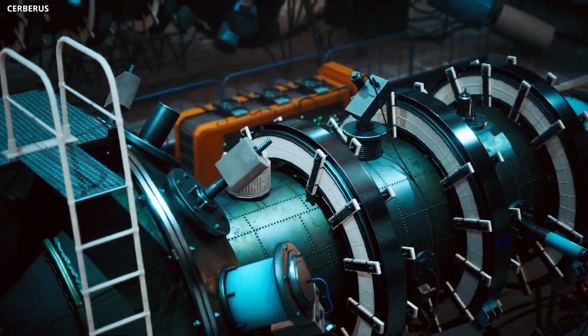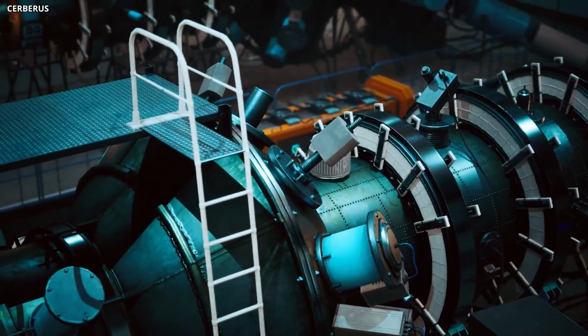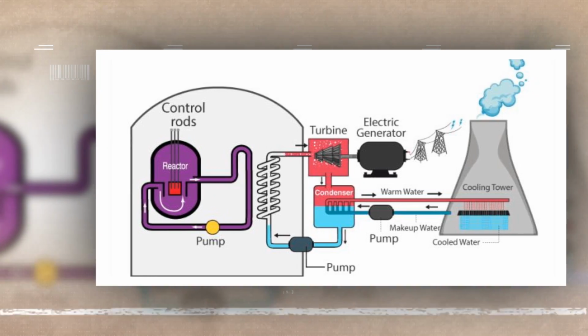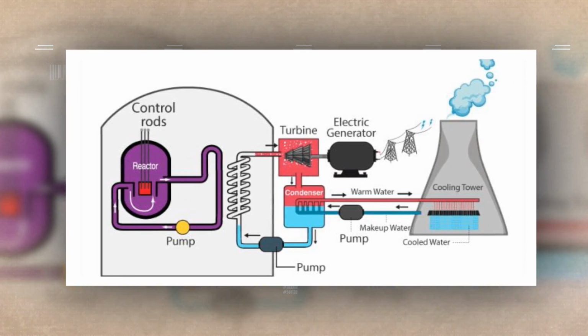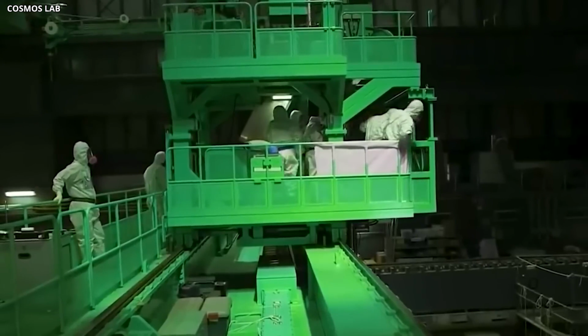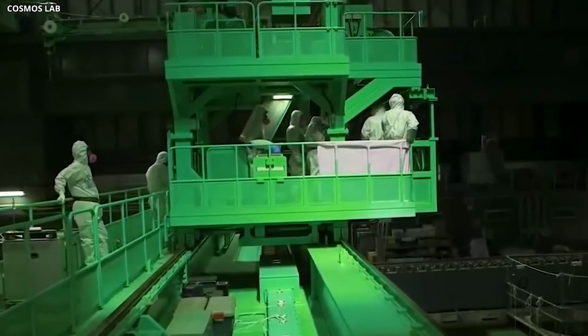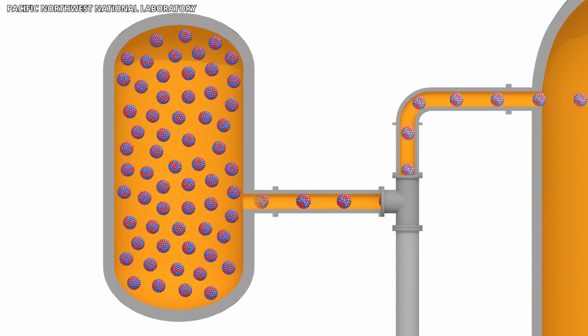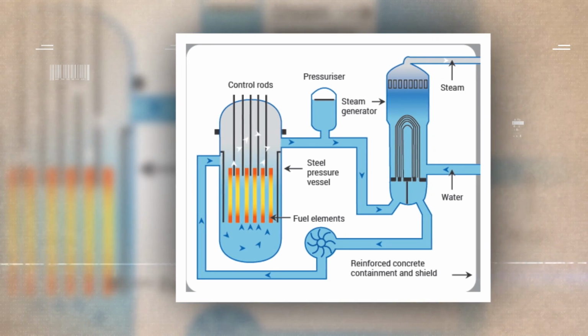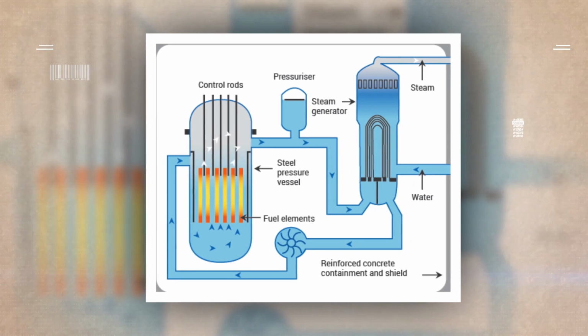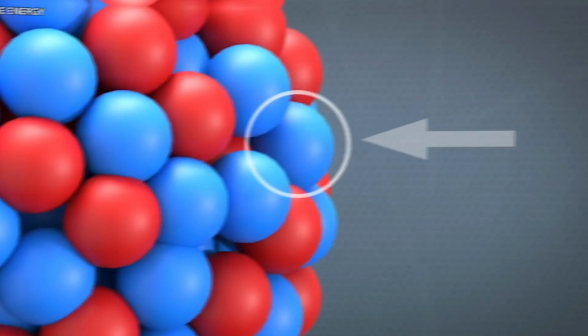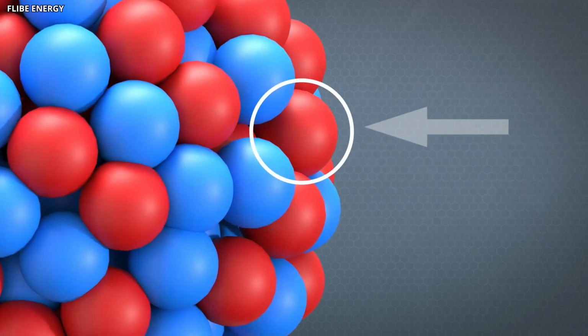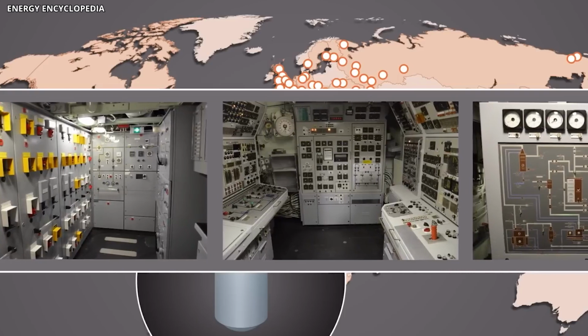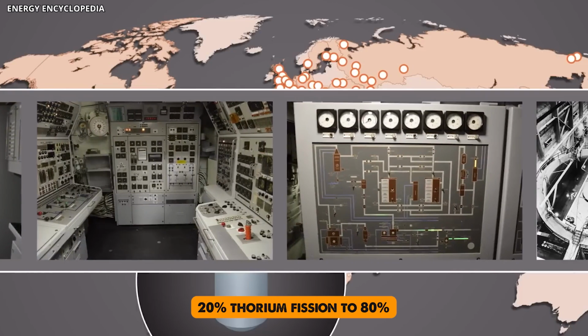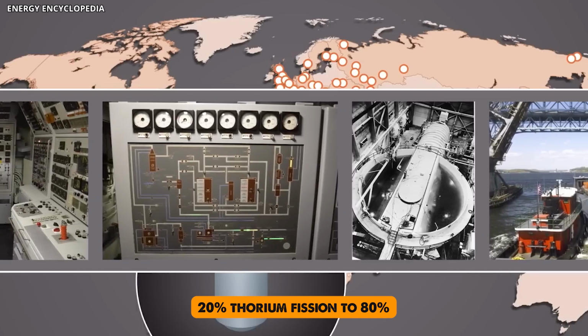During its first few years, the reactor will operate on a batch basis, with some online refueling and removal of gaseous fission products. After 5 to 8 years, all the fuel salt will be discharged for reprocessing, where fission products and minor actinides will be separated for storage. The reactor is made to achieve a repetitive recycling process of uranium, salt, and thorium with online separation of actinides and fission products. Over time, the reactor will move from about 20% thorium fission to around 80%.